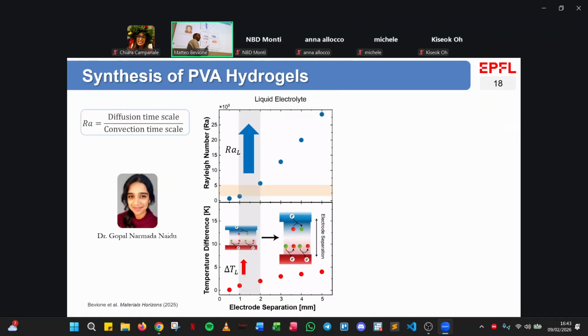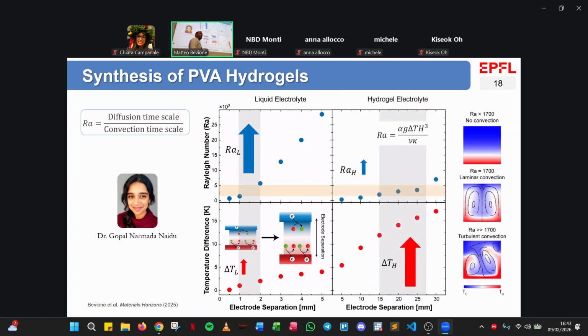The beauty of that is that we developed also a simulation to understand if this was really possible to then get a large temperature gradient. In this graph, what I'm showing you is precisely what I said, that using just liquids, generally what you get is that you end up pretty soon in a turbulent regime. So irrespective of how thick you make your cell, still you cannot get a very large temperature gradient. So that's very important for us. We then also simulated the hydrogel, and with this material, we could refrain to go into a turbulent regime and really get a very nice temperature gradient. So I was very happy about this result.